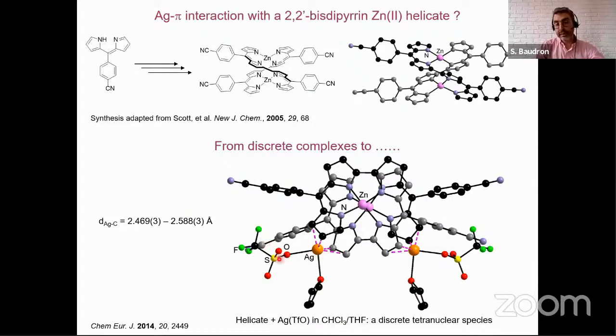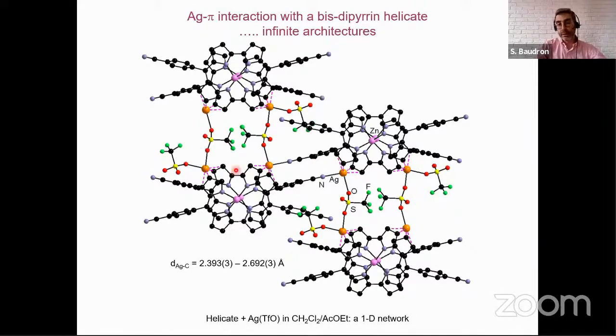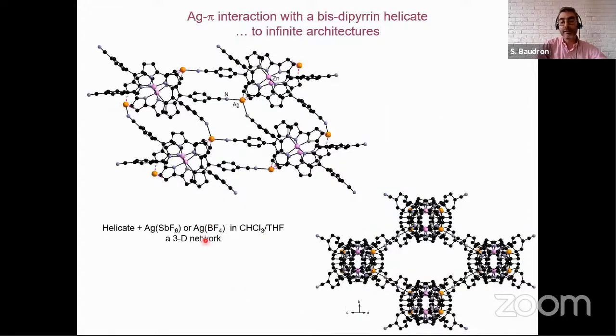So playing with those two, the anion and the solvent, we were able to go from the discrete tetranuclear system to coordination polymers. Indeed, replacing THF by ethyl acetate, we obtain a one-dimensional coordination polymer, still with this recurrent tetranuclear motif with 1 helicate and 2 silver 1 cations complexed via silver pi interaction, and the coordination sphere of the metal cation is completed here either by triflate anions or by the peripheral nitrogens. Replacing the triflate anions by less coordinating anions, such as tetrafluoroborate or hexafluoroantimonate, we obtain a 3-dimensional system where once again we have a silver pi interaction and interaction of the nitrogen with the silver.